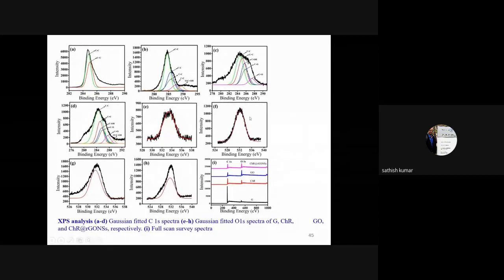Here you can see the carbon core level spectrum clearly shows the restoration of the carbon-carbon bond, and it also conveys that the graphene oxide is successfully converted into graphene, reduced graphene oxide, and the presence of all these functional groups highlights that the chrysene is being functionalized on the surface of the nanosheets.